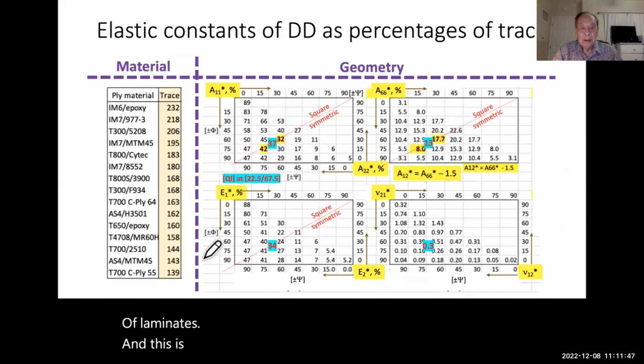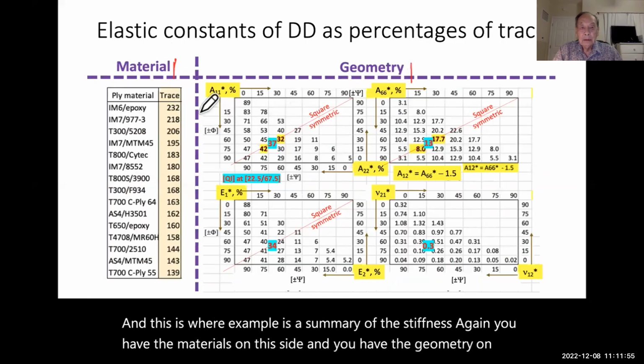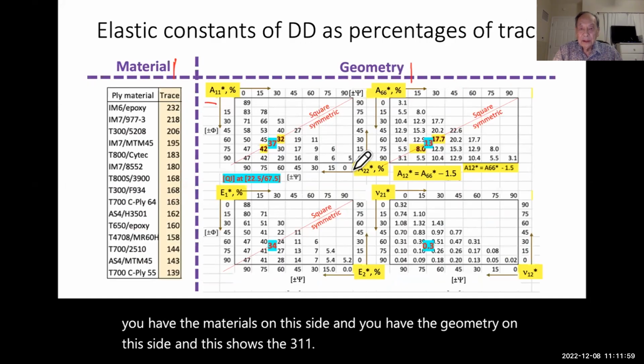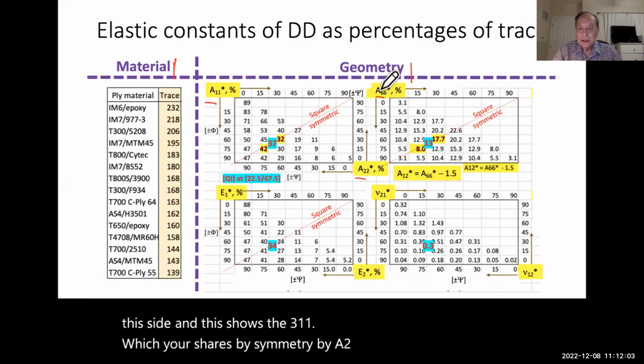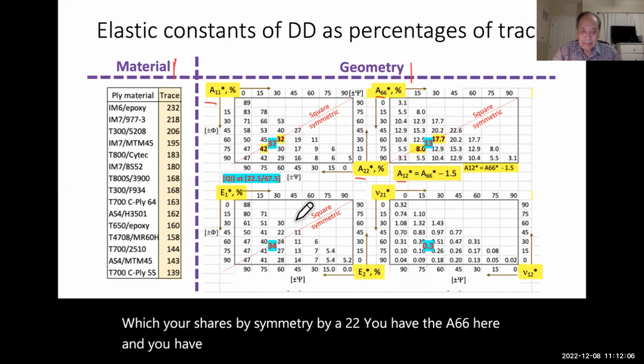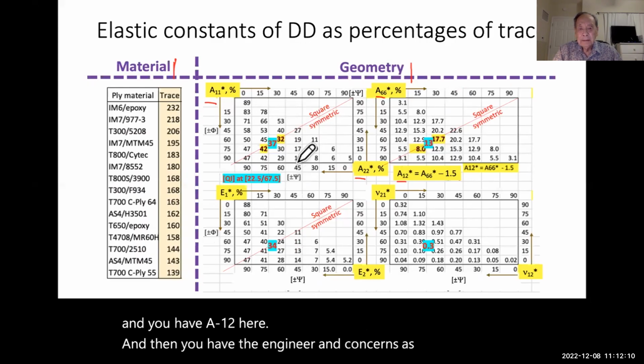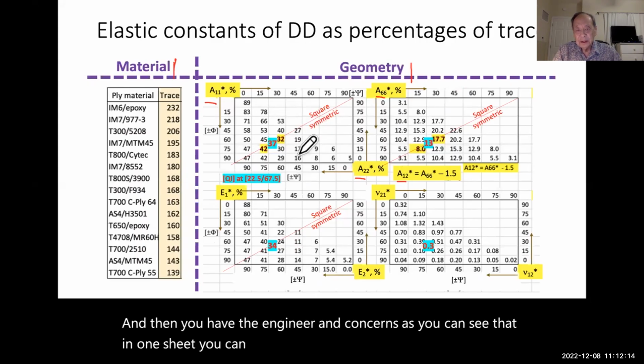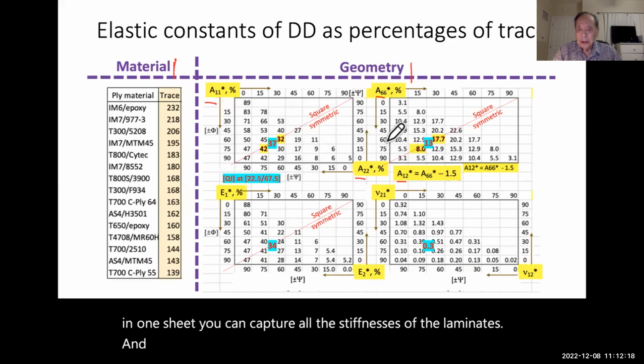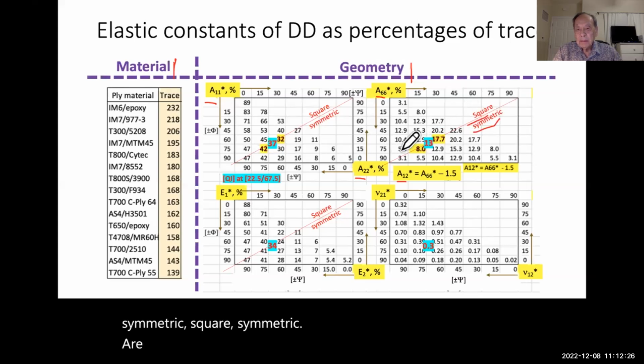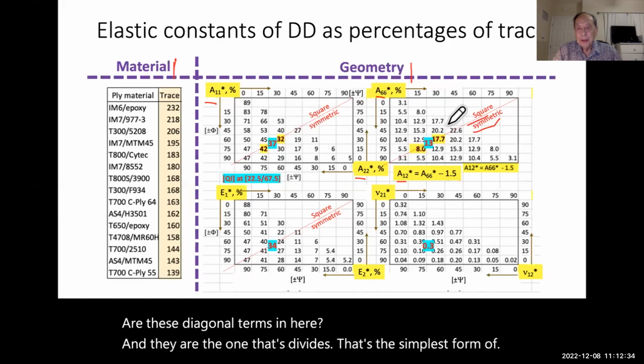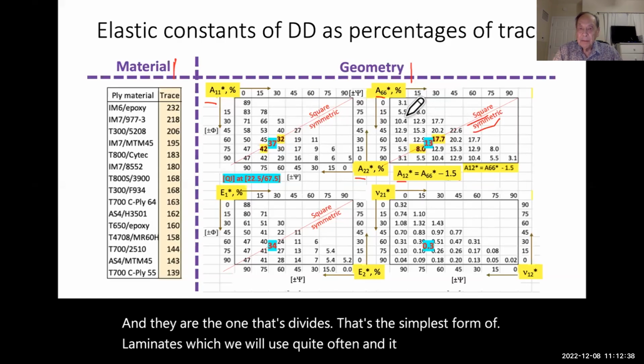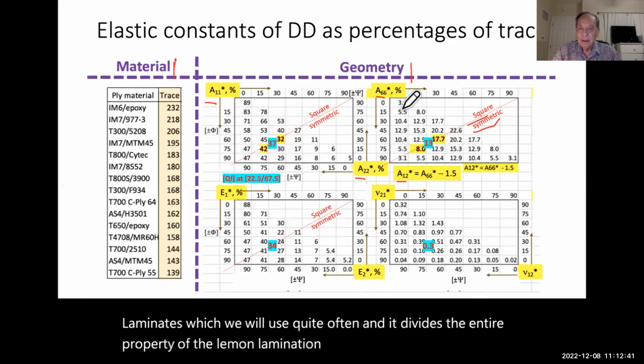And this, for example, is a summary of the stiffness. Again, you have the materials on this side, and you have the geometry on this side, and it shows the A11, which is shared by symmetry by A22. You have the A66 here, and you have the A12 here, and then you have the engineering constants. As you can see, in one sheet, you can capture all the stiffnesses of the laminates. And then in particular, we made a special one, this is square symmetric. Square symmetric are these diagonal terms in here, and they are the ones that divide. That's the simplest form of laminates, which we will use quite often. And it divides the entire property of the laminates into two parts, what is above that and what's below that.